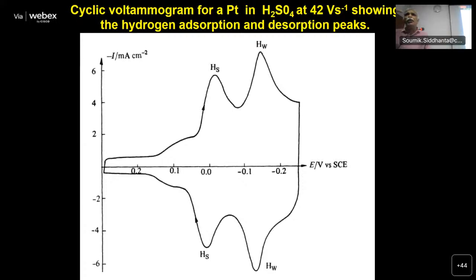So this method is used by many electrochemists to calculate electrochemically accessible surface area using materials. This is of course polycrystalline platinum, but platinum nanoparticles you can also do. So we are looking at the hydrogen side of polycrystalline platinum, where hydrogen gets adsorbed because you are going to the minus side, minus 0.2, minus 0.1, 0. Accurately, you need to use a very good reference electrode for these types of measurements so that quantitatively the quantity of hydrogen adsorbed in first site and second site can be determined.